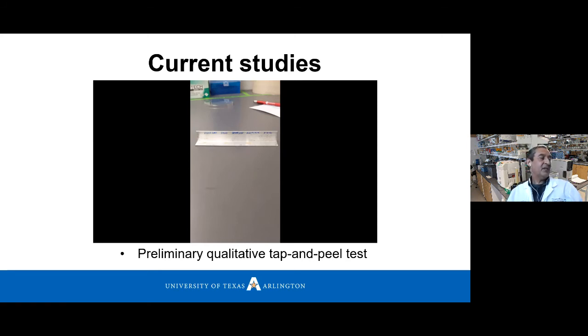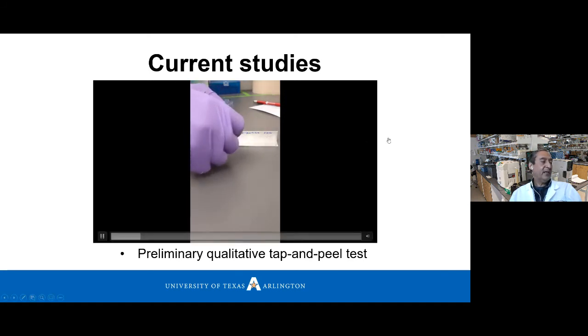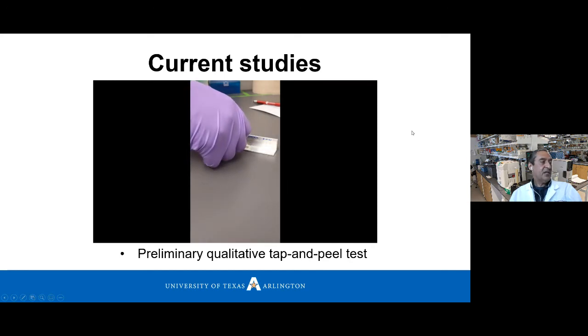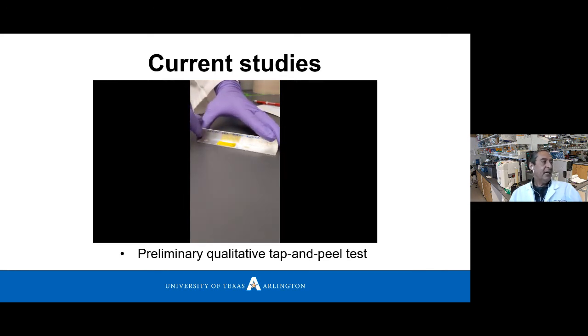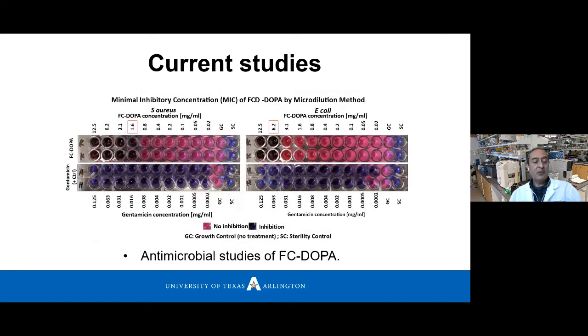It's just a video where it shows what is called the tap and peel test. Well, basically, we just put a piece of tape on top of the hydrogel, and then we quickly remove the tape, and we observe if there is any kind of dislodging of the material. And this is a quick qualitative test. Of course, later on we will perform more studies, more on the quantitative aspect. But in this case, the material was able to pass the test.